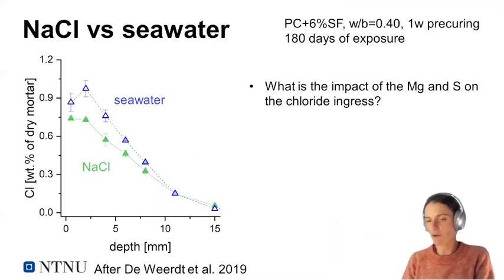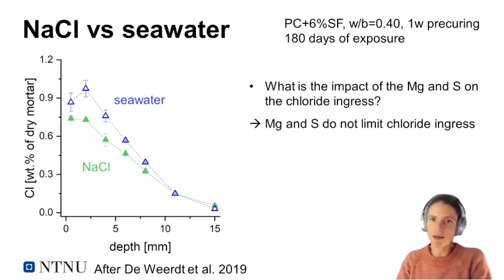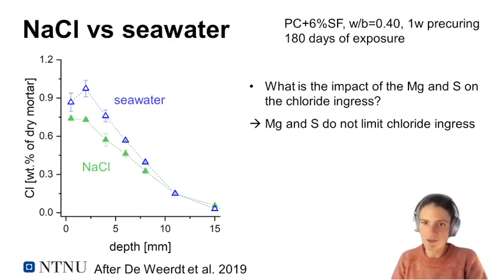What we're seeing here is the chloride profiles for the seawater exposed and sodium chloride exposed sample. And we see that the seawater exposed sample has the highest chloride levels and a slightly higher, one could say deeper ingress compared to sodium chloride. So what this is showing is that actually if sulfur and magnesium would be reducing your chloride ingress, the seawater profile should be below the sodium chloride profile, but it isn't. So we can actually, based on these results, conclude that magnesium and sulfur do not limit the chloride ingress.